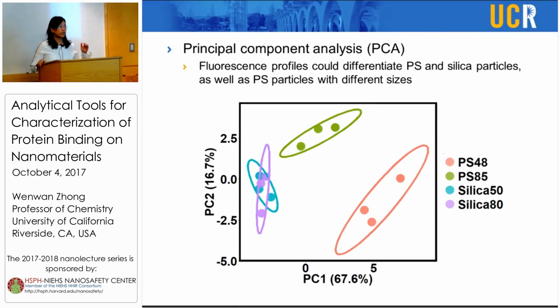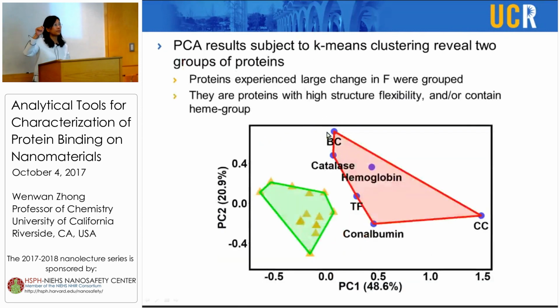So when we no longer control the surface amine density, these 2 batches of silica, although they have the same core size, 50 to 80 nanometer, are no longer separable. But for the polystyrene particles, we still see that the 48 and 85 nanometer sizes have quite significant differences in protein interaction. But if we use the fluorescence profile, using the particle as the variable to group the proteins, like I said, it's very hard to find a particular feature that we are familiar with for the protein, to see whether it's a larger protein that binds stronger or a more positive protein that binds stronger. We didn't see that kind of relationship.